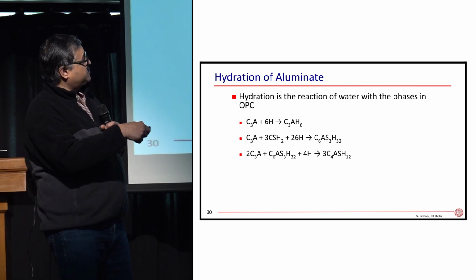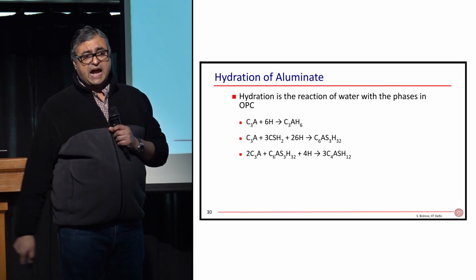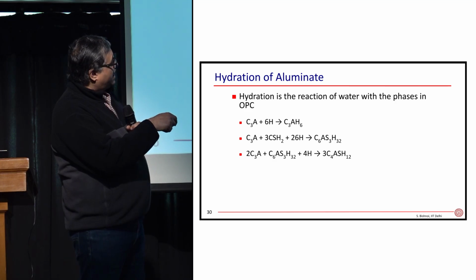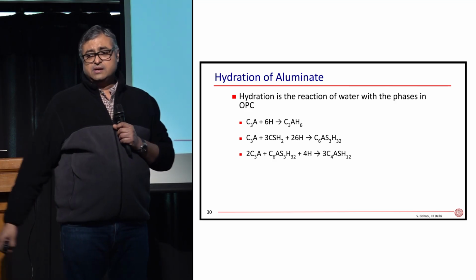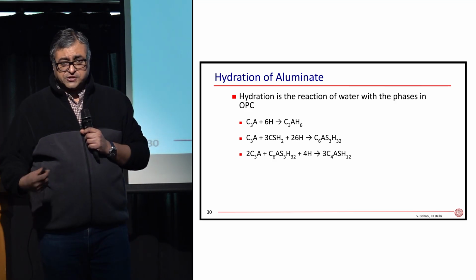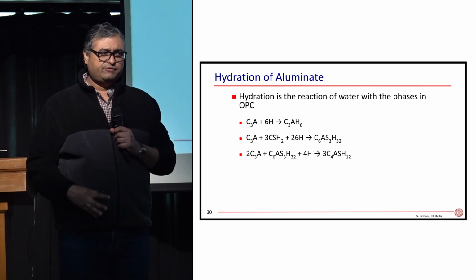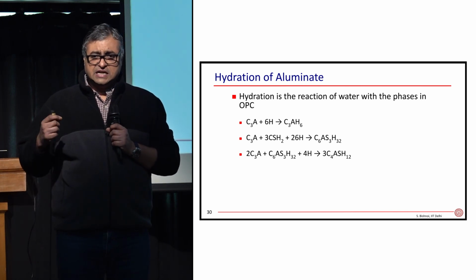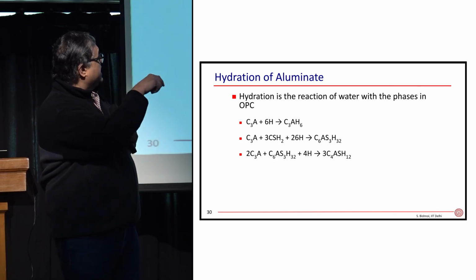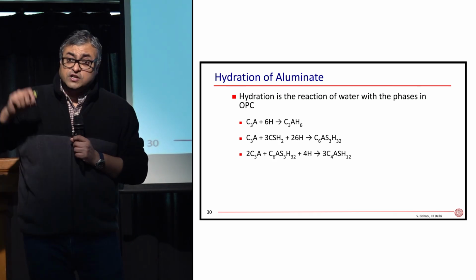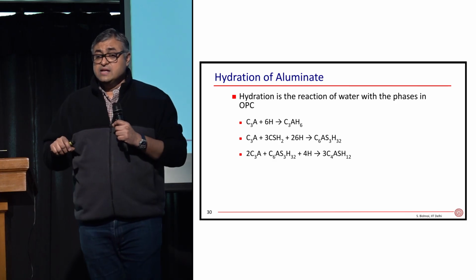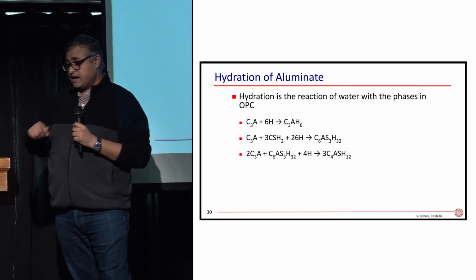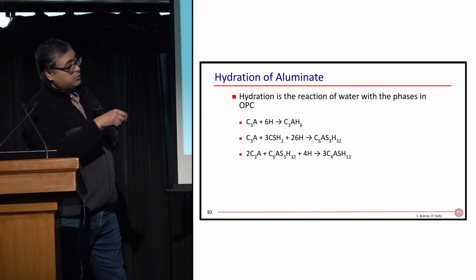So it reacts with the gypsum, produces something known as ettringite over here. This should be S bar. That is calcium aluminosulfate. It's also known as the AFT phase. This ettringite produces needles, but the important thing is its reaction is slower. It's still a very rapid reaction, one of the first reactions that happens in cement. But then this reaction is slower than the production of hydrogarnet over there.